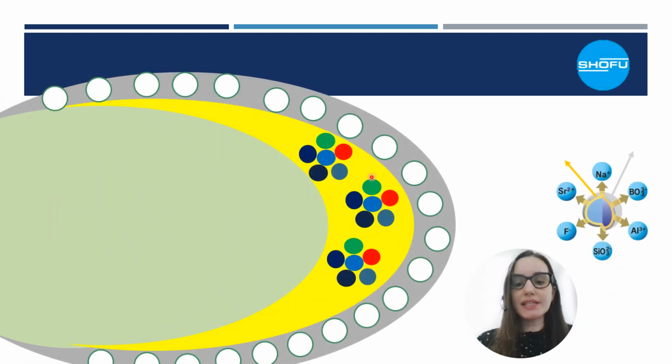So, this is the glass ionomer layer, and let's take a look at the entire particle surface to understand it better. Here we have the glass ionomer layer, the yellow one, with approximately 50 nanometers. The modified surface layer, this one which is porous, has around 200 nanometers. And in association with the glass core, the entire particle is around 3 micrometers.